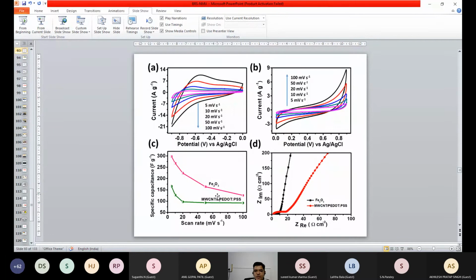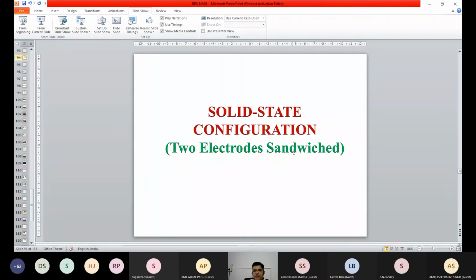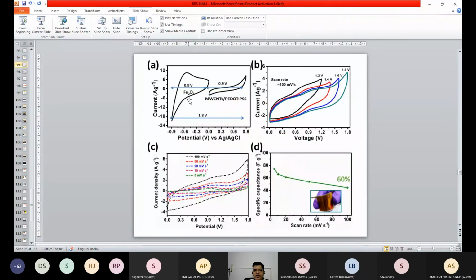This is a single Fe2O3. This is carbon nanotube with the PEDOT:PSS, right? This one shows the voltage window of 0 to minus 0.9, and this is the voltage window for the other one, from 0 to 0.8. Here you can get the solid state idea. Here Fe2O3 has the voltage window from 0 to minus 0.9, which gives a voltage window of 0.9. This is in the negative region. And when you have the polymer coated on the carbon nanotube, it gives the voltage window in the positive region, that is 0 to 0.9.